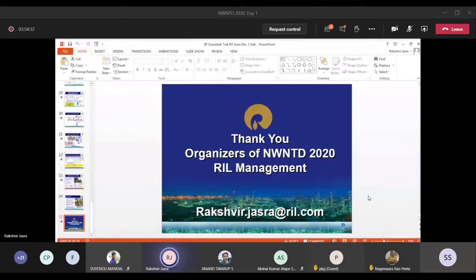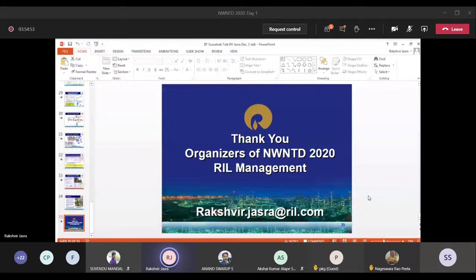As I told you, when you use a support it is very important. Any support, normally alumina or silica, has hydroxyl groups on it. So we have some hydroxyl groups on this alumina support, which already has the metal deposition done on it. These hydroxyl groups then react with something like triethyl aluminum. These alkyl aluminum compounds are very reactive. The moment they see an OH group, they will immediately get hydrolyzed, and you keep the concentration such that it only forms a monolayer on the alumina surface. You can even calculate the surface density of hydroxyl groups, and accordingly put in the TEAL amount.